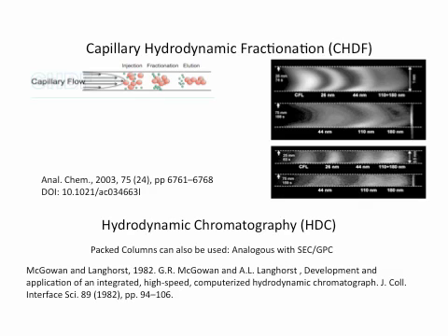They don't have this drag force, so they basically get drawn to the middle. As a result of that, you separate the different sizes. So large particles come out first, small particles come out last, simply by playing with the flow. And here you see some nice images of this actually happening. So you see particles, again filmed with dark field, of 26 nanometers coming out last, then a band of 44, and then a band of 110 plus 180. So it's a very elegant way of separating particles of different sizes.